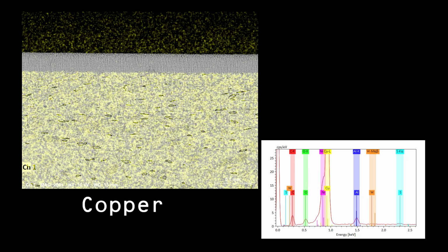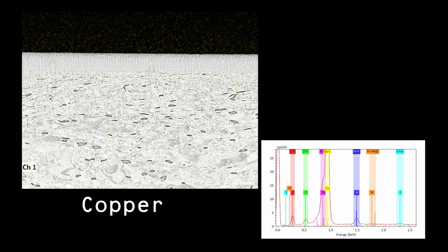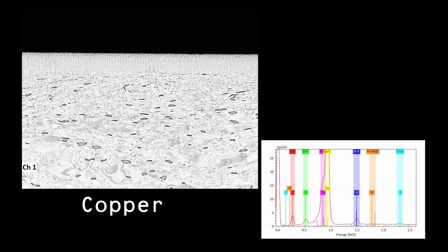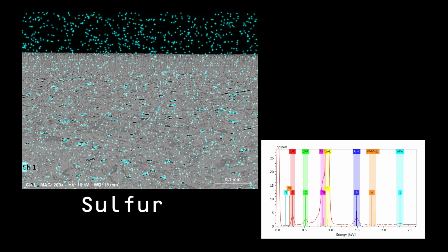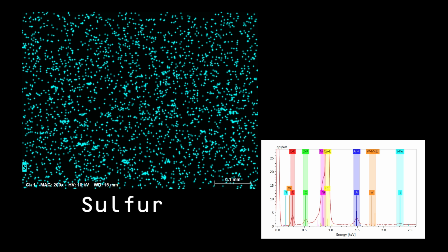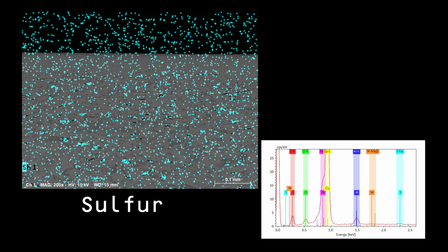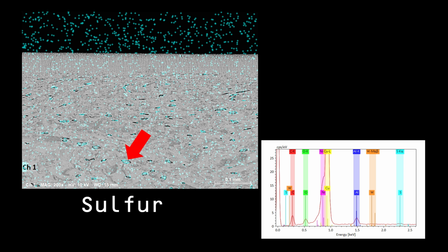The bulk of the bullet is obviously copper, so no surprises there, except that one thing I do see is in this copper, there are these small bits of sulfur floating around. Now, overall, it's a very small amount, like around 0.25 weight percent, which is practically nothing. I mean, the reason I say it's strange is that sulfur and copper don't get along very well, and normally you wouldn't want them together at all. But in such small quantities, I'm not really concerned. I just don't know why it might be there.